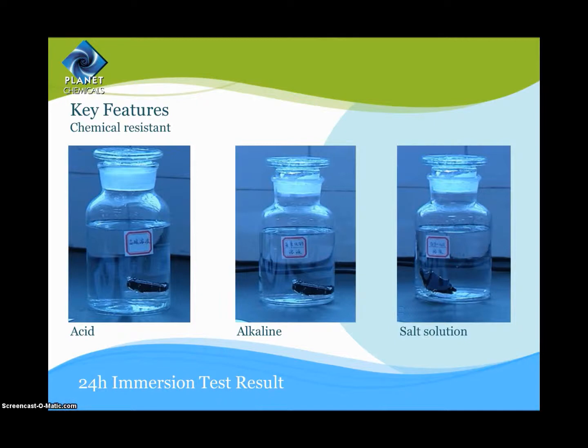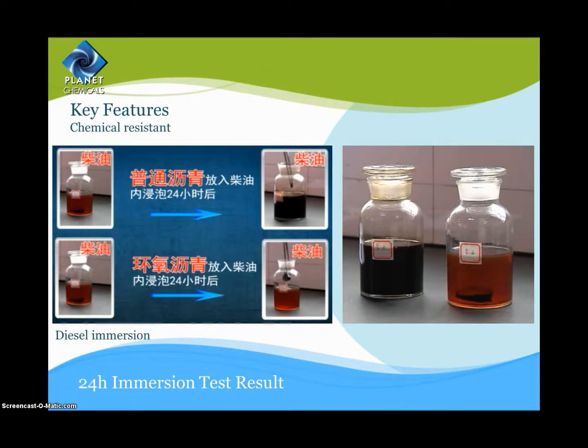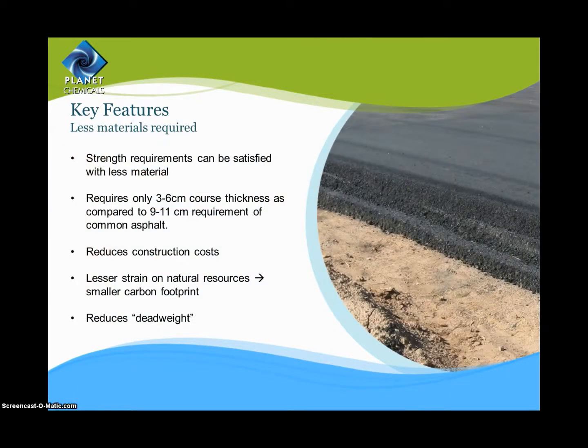Immersion tests were carried out in various solutions: acid, alkaline, salt, and diesel. These tests revealed that even after being immersed for a period of 24 hours, there were no changes to the physical and mechanical properties of the test specimen. It was also noted that even after a 2-week immersion in diesel, the aggregates from the specimen did not show any signs of loosening. This clearly shows that epoxy asphalt pavements can meet the standard of oil corrosion resistance.